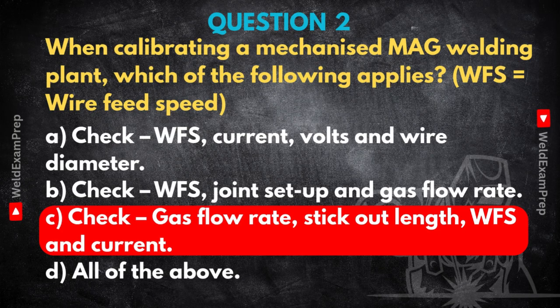Sure. Gas flow rate: you need to know the machine is delivering the correct amount of shielding gas. Too little means contamination, porosity. Too much can cause turbulence or just waste gas. That's a machine setting you verify. Makes sense. Stick out length, the distance the wire protrudes from the contact tip. This affects electrical resistance, influencing voltage and penetration. While the operator sets it initially, verifying consistent control is part of ensuring the system works right.